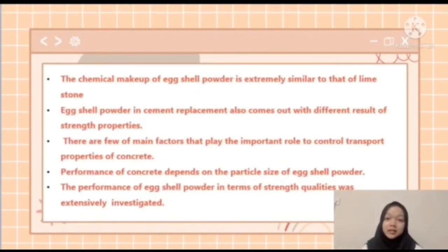For the discussion of this experiment, point 1: the chemical makeup of eggshell powder is extremely similar to that of limestone. This is as stated earlier, because eggshell powder and limestone can be tested in the same situation of replaced concretes in strength property. Point 2: eggshell powder in cement replacement also comes out with different results of strength properties. This can be seen that eggshell powder can come out with high or low strength of concrete after being tested, according to the percentage of eggshell powder added into the concrete mixture, and it also depends on the age of the curing.